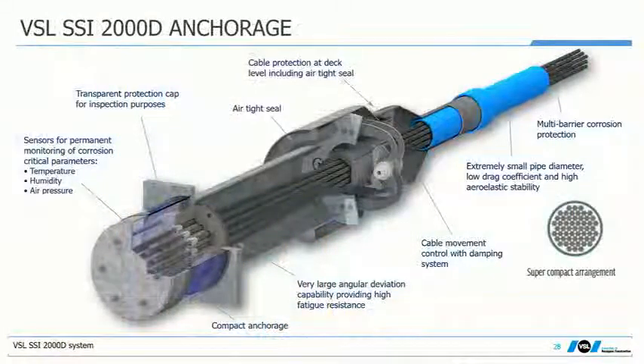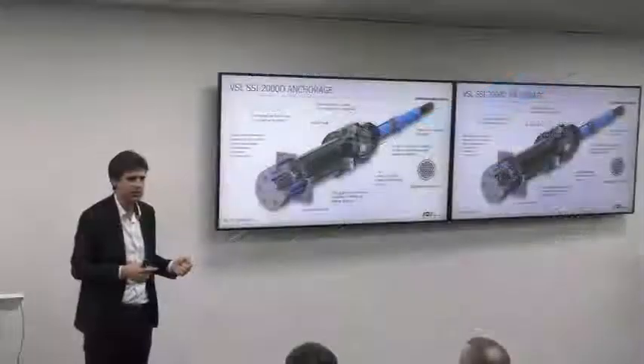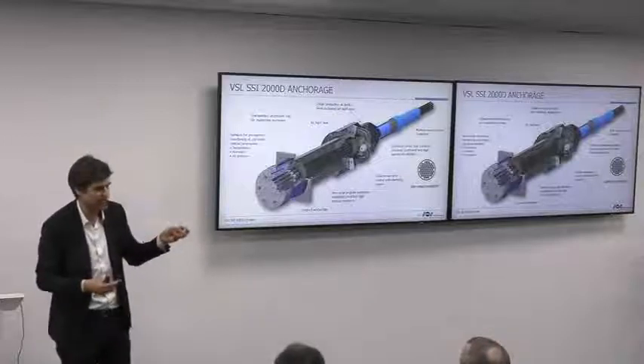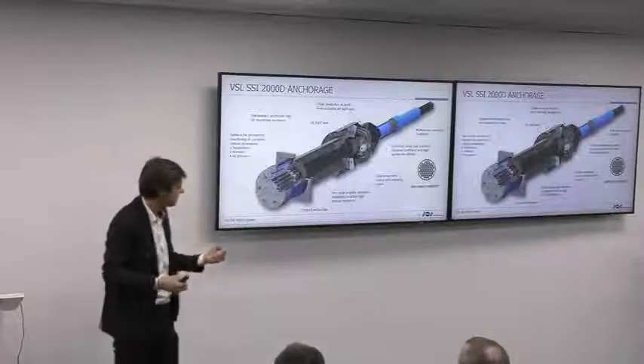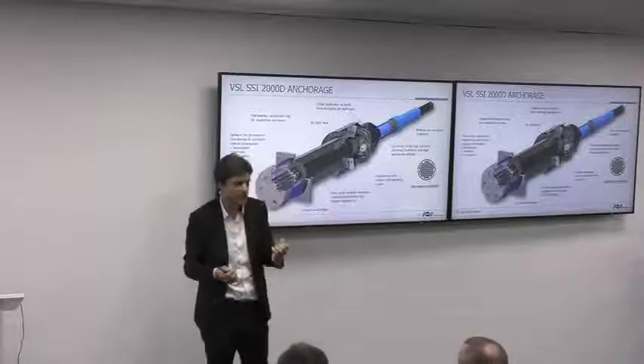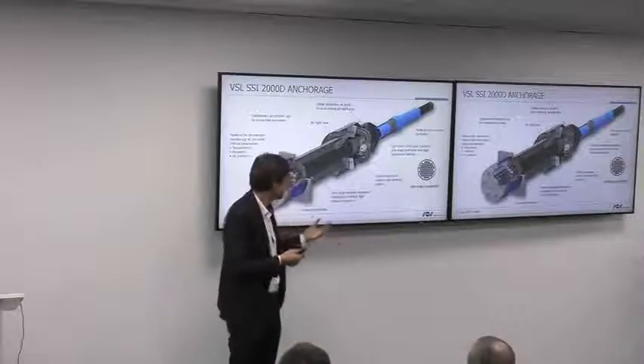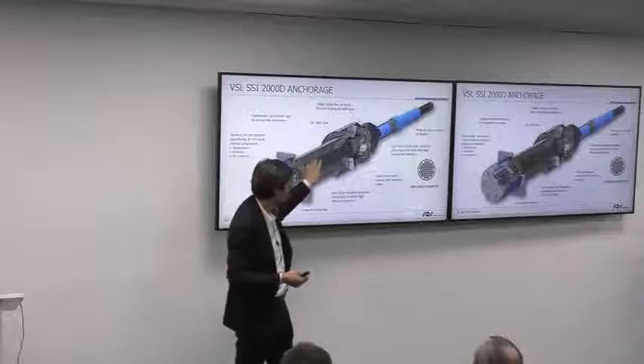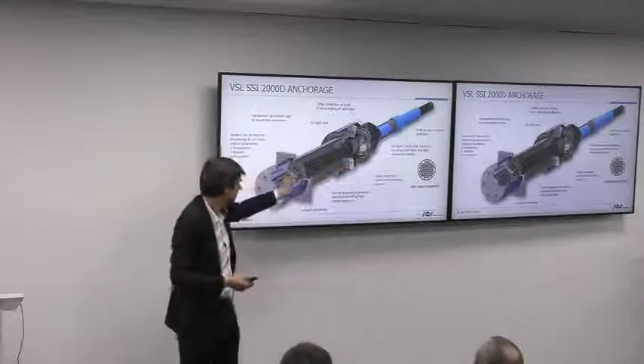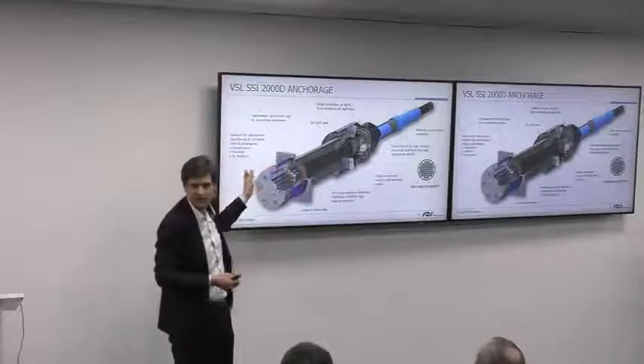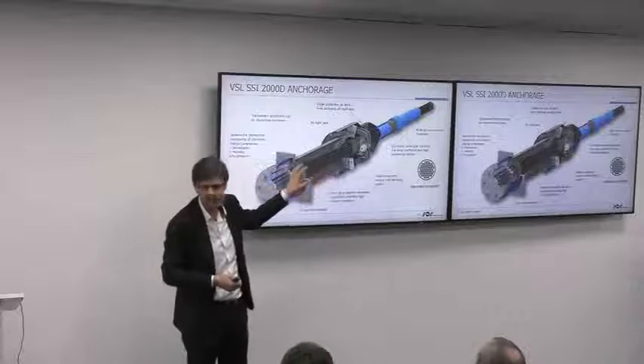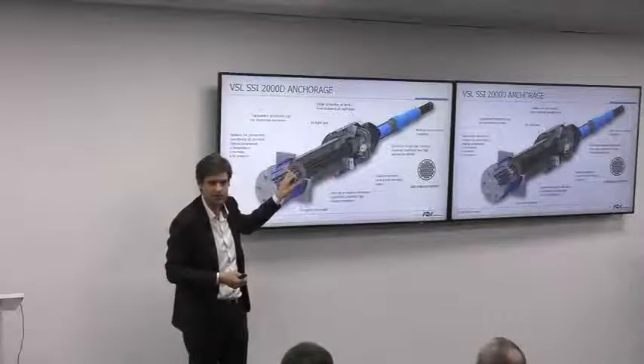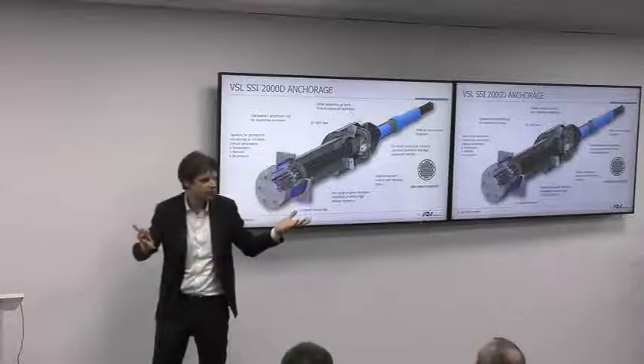This is a development that VSL started like 15 or 20 years ago. We call it the dehumidified system. We depart completely from the requirement we have today, or the recommendation, which calls for strand with wax injection, sheeting, a lot of petroleum-based material inside. And we replace this passive corrosion protection with an active corrosion protection. How it works is the stay cable system, or the steel main tensile element, including the anchor head, is in a fully tight encapsulation, and the air inside this encapsulation is dehumidified. The water is removed from that air.